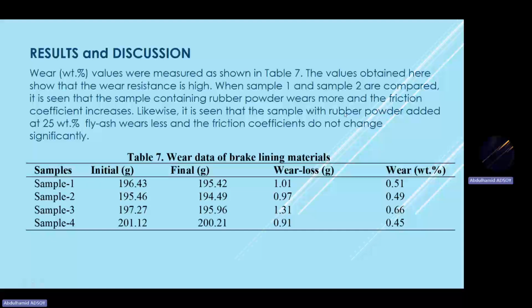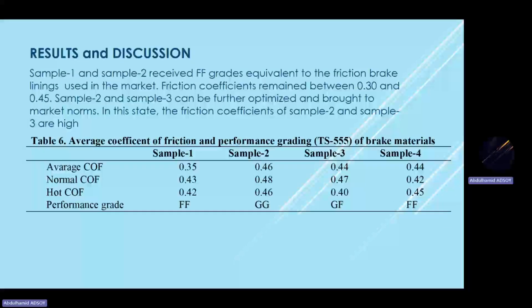Now, if we compare sample 1 and 2, the only difference between these two samples is that sample 1 doesn't contain rubber, and sample 2 contains rubber particles. Now, the samples containing rubber powder wear more. We can see 0.5 to 0.49. And the friction coefficient also increases. We can see it from this table, from 0.35 to 0.46.